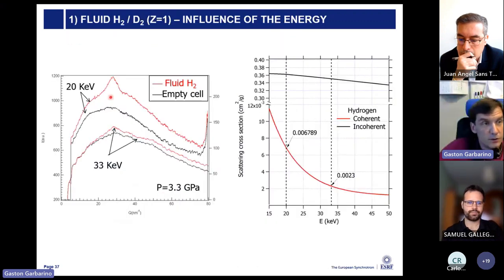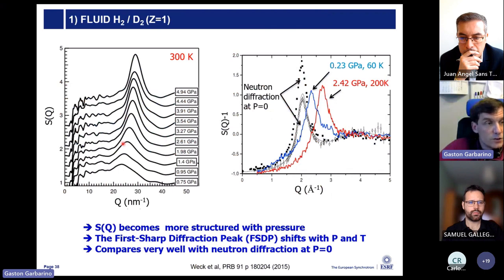So why this was interesting, because if you study, for example, hydrogen, as I said, the signal using the multi-channel collimator at 33 kiloelectron volt, as you can see here, is very low, almost inexistent. But if you reduce the energy, you can see that the broad peak of the first sharp diffraction peak of the liquid is appearing, meaning that we are able to study, even if the signal is weak, this hydrogen at very low pressure and low temperature. So what we did is to follow the position and the intensity of the peak in function of pressure at room temperature, but also at low temperature, and we were able to follow it in function of pressure.